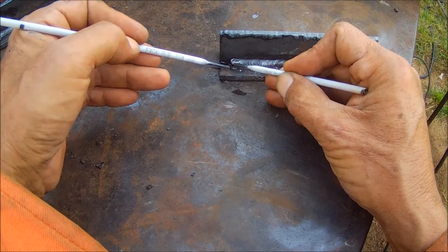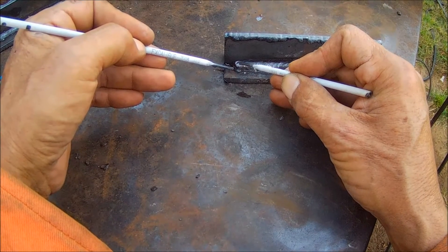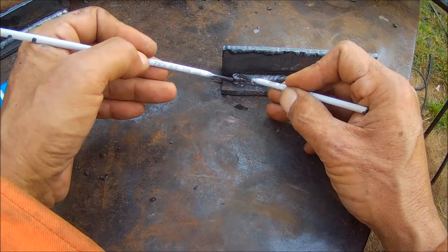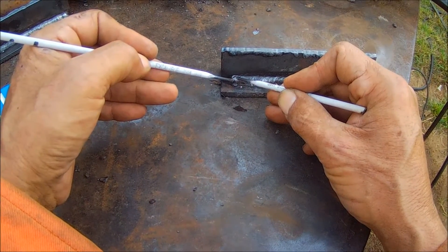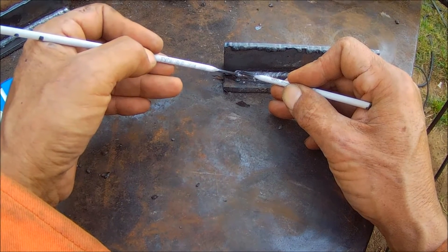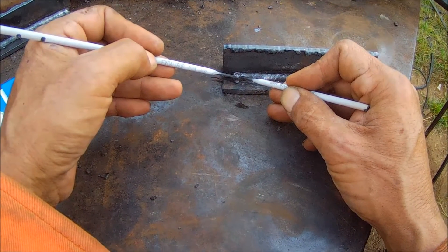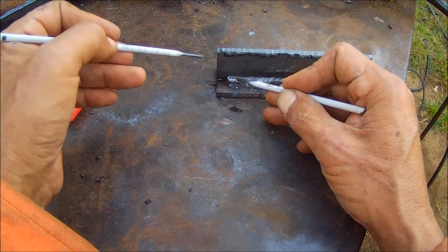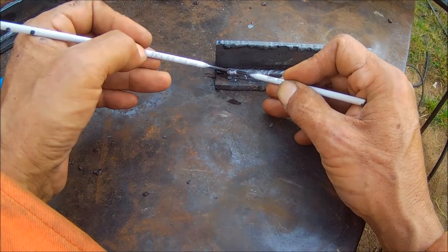At the beginning, I don't know if you saw it, but I paused just enough. And you've got a cold start too. You want to warm it up before you start going uphill anyhow. But I paused long enough to build a shelf. Here's my arc. And I'm just letting it sit for a second or so until I see a shelf down here. Once I see that shelf, I know I've got something for this metal to lay on. So I can start working my way up.